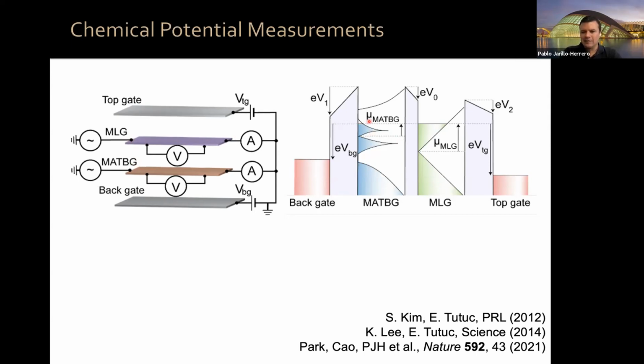This is the band alignment diagram. We have the back gate, top gate. We have the magic angle twisted bilayer graphene with Van Hove singularities, flat bands. And here is the density of states of monolayer graphene. This is the density of states of magic angle twisted bilayer graphene. So it turns out, and you can look at the details in this paper, if you monitor R_XX, the resistivity of magic angle twisted bilayer graphene, that gives you information about the chemical potential in monolayer graphene. And if you monitor the resistivity of monolayer graphene, that gives you information about the chemical potential of magic angle twisted bilayer graphene.